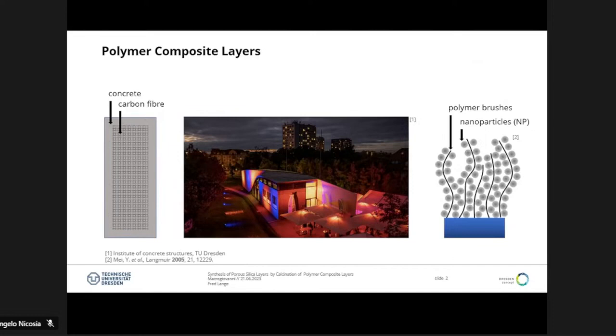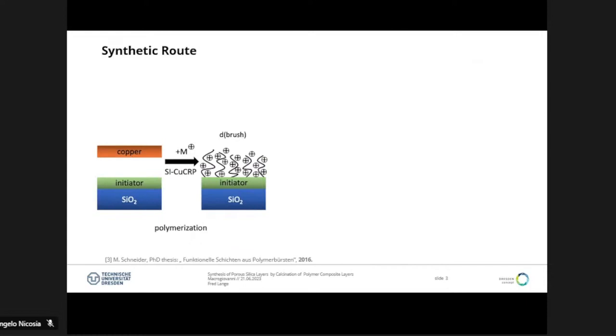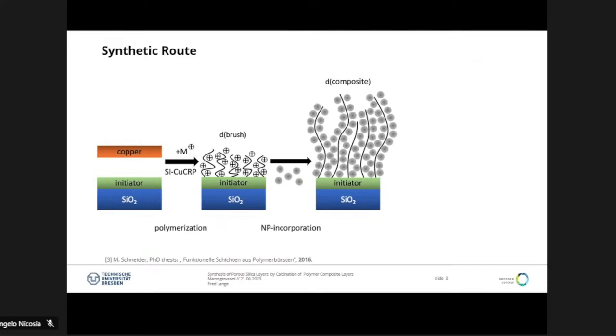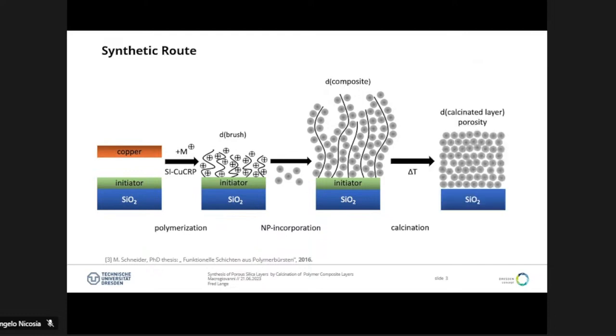My synthetic route to achieve this is to start with initiator-coated substrates and then perform surface-initiated copper-mediated controlled radical polymerization with a cationic monomer to achieve cationic polymer brushes. Those cationic polymer brushes can then interact with negatively charged particles to form a composite like I explained on the last slide. In a subsequent step, high heat can be used to calcinate, which means to remove all organic compounds, which then results in a porous layer of the beforehand embedded particles. And this layer can be characterized by its porosity.